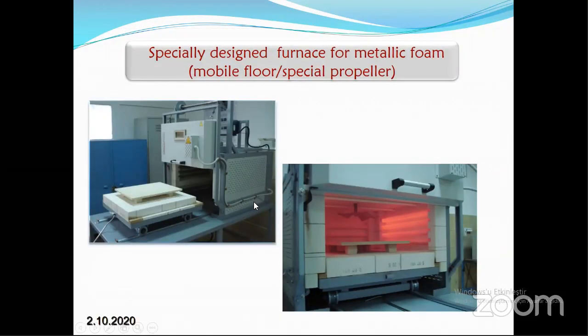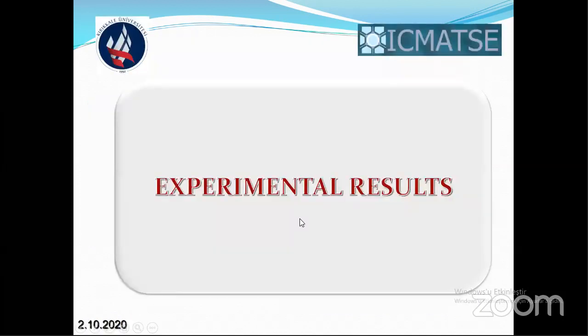In order to produce very big metallic foam, we specially designed a furnace, the mobile floor. So whenever we want, we take the sample out. And this furnace also contains a special propeller to get a homogeneous distribution of the temperature inside the furnace.